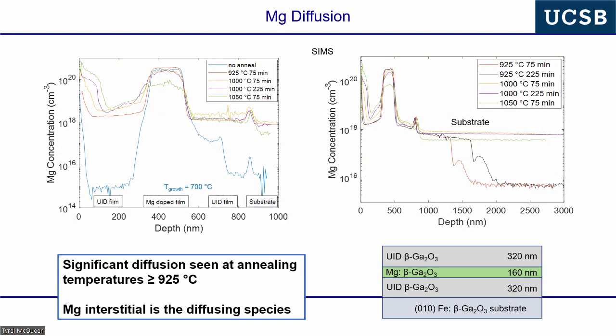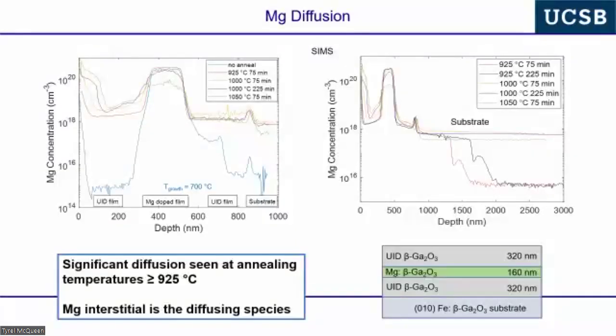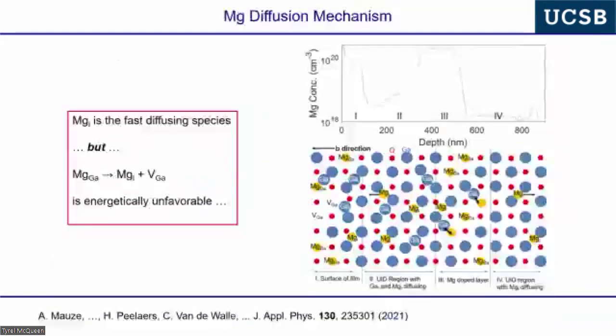And this is kind of remarkable. You see here the magnesium concentration with increasing annealing temperature. This is acting as a reservoir for the magnesium. This is going down. The magnesium is going out, back into the bulk and to the surface, and at some point it's going all the way through the substrate. We spent a lot of time puzzling over this. This is work I did with the modeling for this.